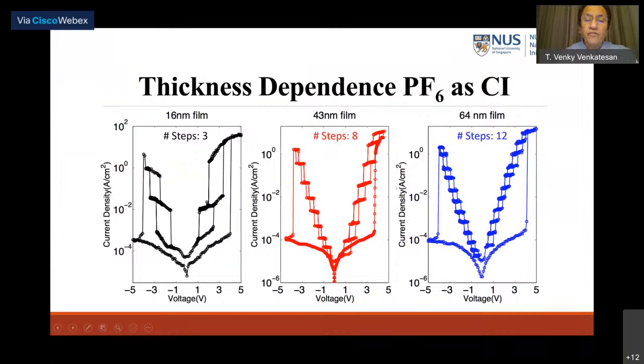And the reason we are able to do this is because our indium bottom electrode is atomically flat, I mean, literally atomically flat. If we introduce, say, half a unit cell of roughness, this effect goes away. So you can't see this effect. So this really needs an atomically flat substrate.